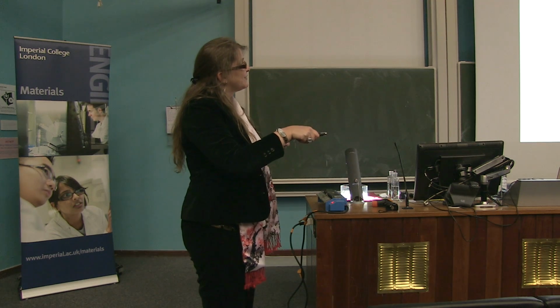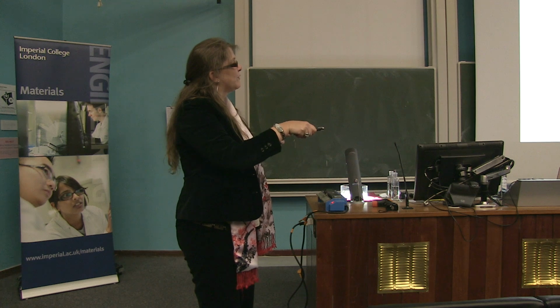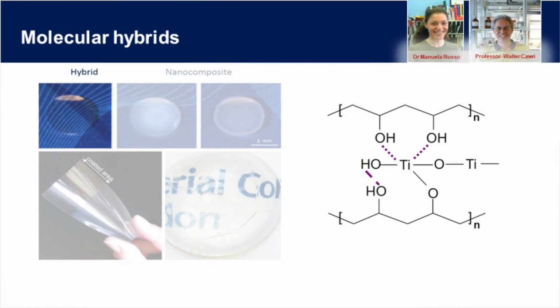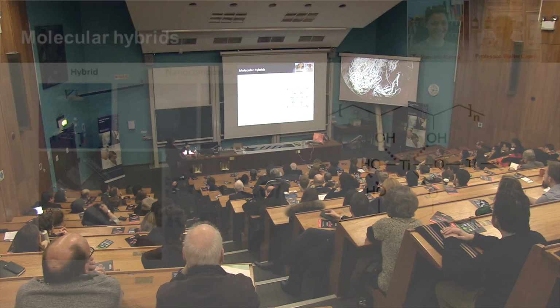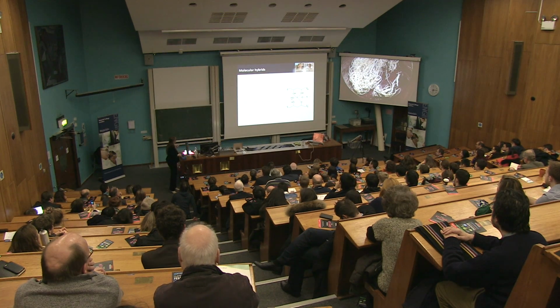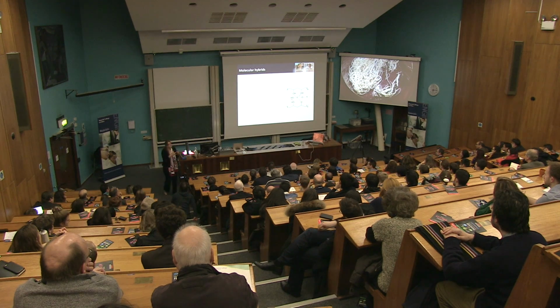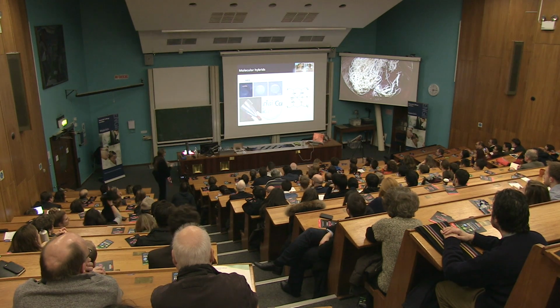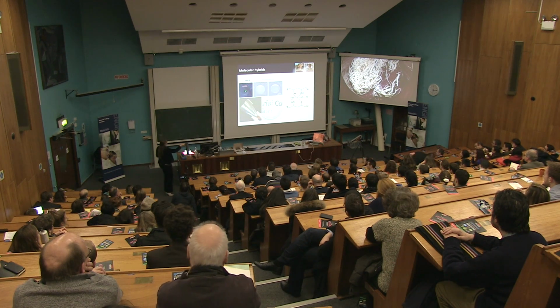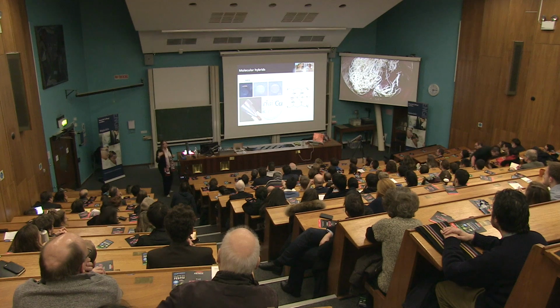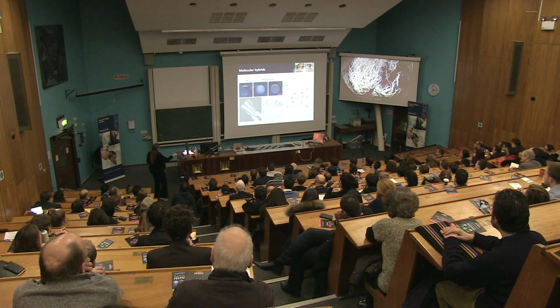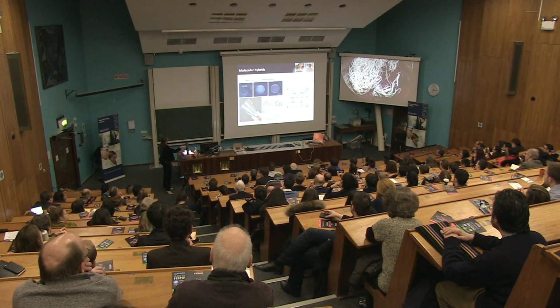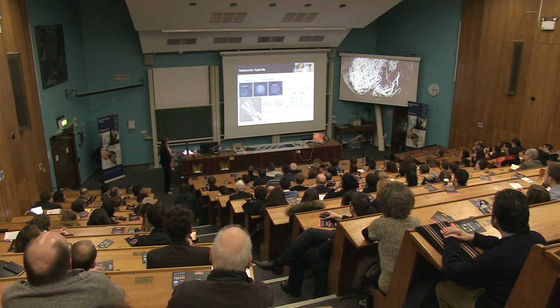And rather than making particles, you see what we try to do is really mix them on the molecular level. So we have metal or other inorganic species combined with polymers. So we always make these signs to show these are long spaghettis, and simply tells you then how many times this is repeated. And because you really mix them on this molecular level, calling them molecular hybrid, you see now when you make a film, you don't have scattering anymore because this mixing is on the very few nanometers level. And again, very different than in case you would take all these titania, oxygen, and making particles out of them.